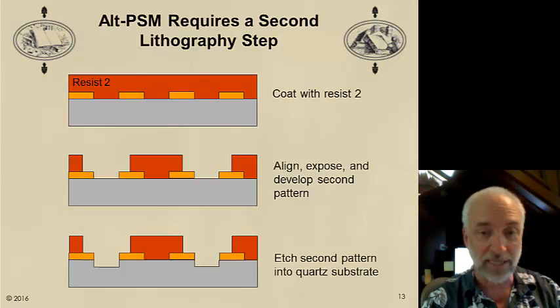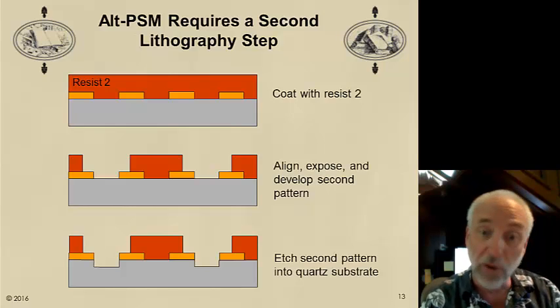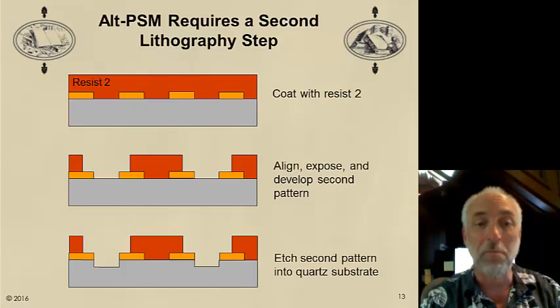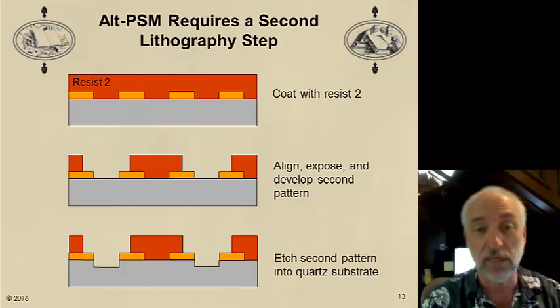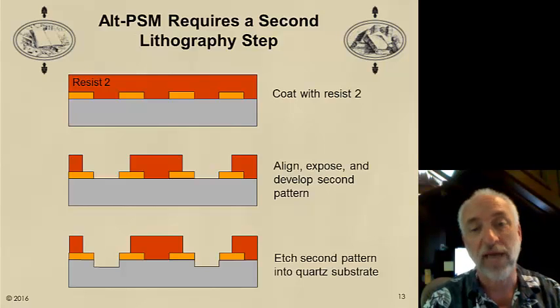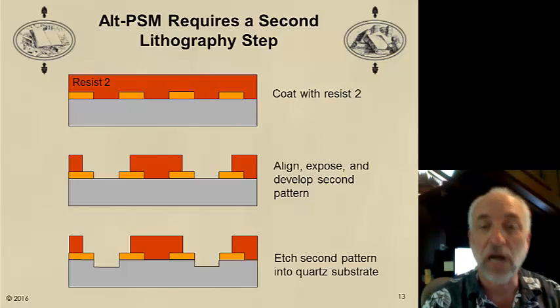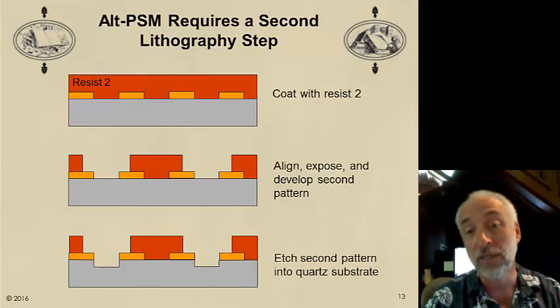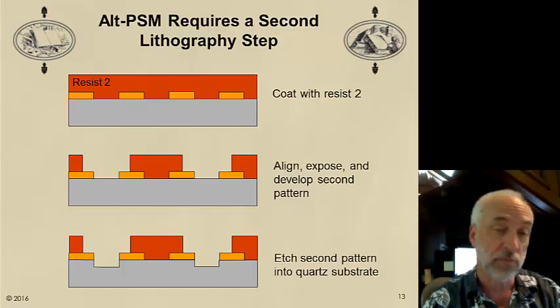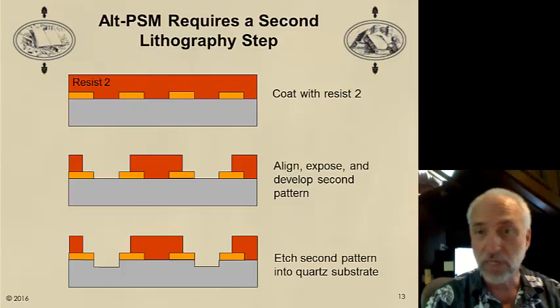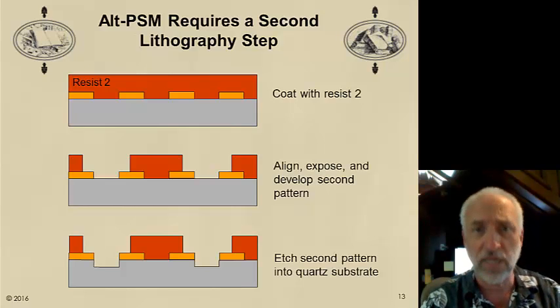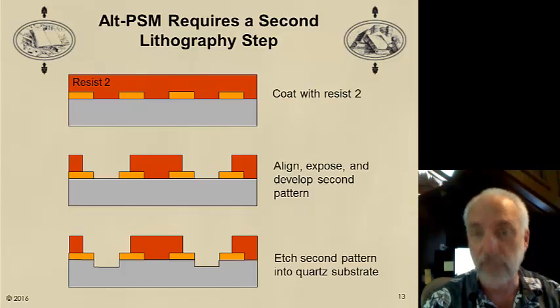And this is something that's interesting and difficult as well. There's no etch stop layer. There's nothing that will make us stop at the exact right thickness. Instead, we have to carefully control the etch rate and the time, to get to the thickness that we want. And that's not an easy thing to do either. So you can see that with the alternating phase shifting mask process, there's quite a few new steps and extra steps. Additionally, there's extra inspection steps.